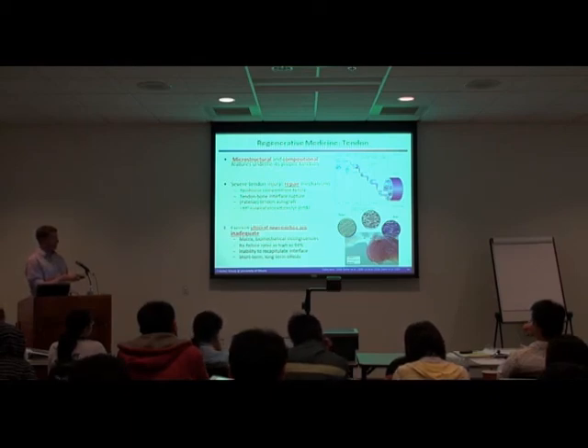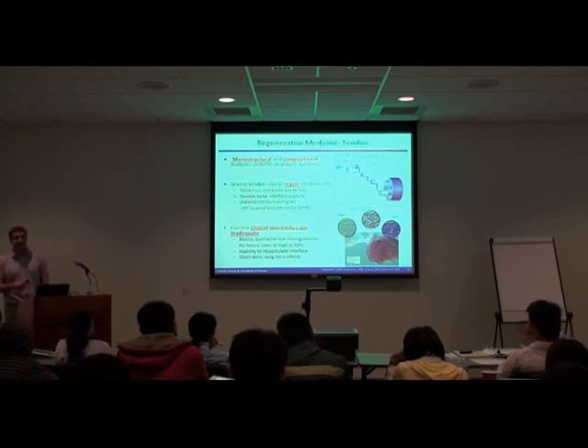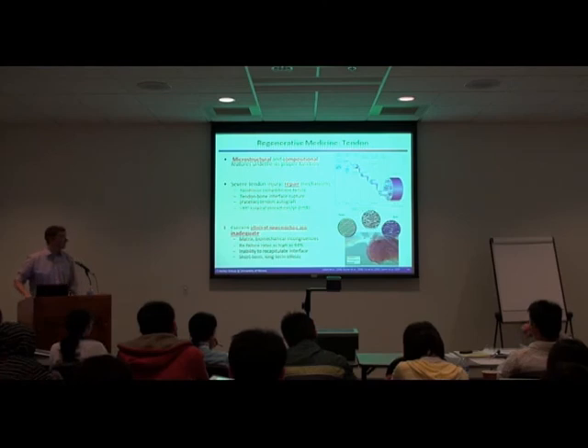We start to see more and more calcium phosphate mineral, less and less alignment, and a high proteoglycan content right at the interface. Then you end up with an isotropic, highly mineralized bone structure. So again, can we actually make these types of structures with our materials?